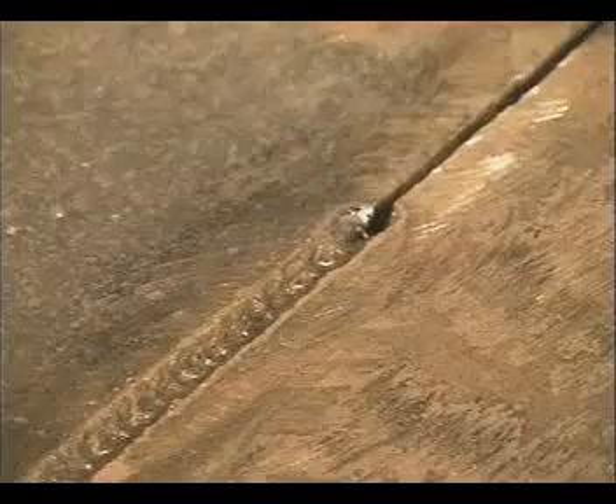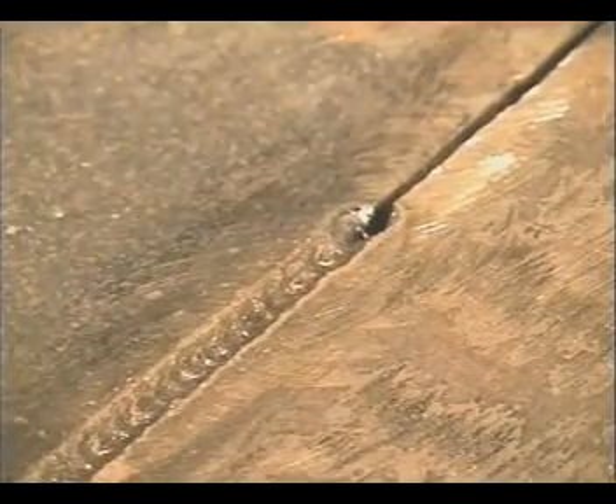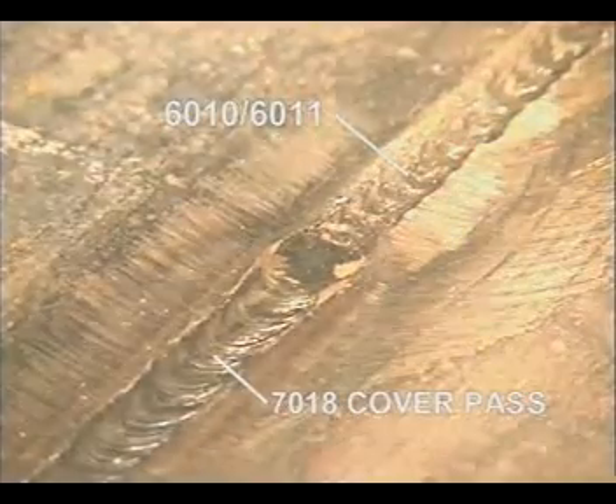6010 is used strictly on DC plus and 6011 on AC or DC plus. The strong arc force of these rods can blow off rust and paint, making these a good choice for repairs or modifications where the metal can't be completely cleaned. Also, these rods are often used as a first pass to provide deep penetration or to fill gaps and fit-ups that are less than perfect, then covered with a filler rod.